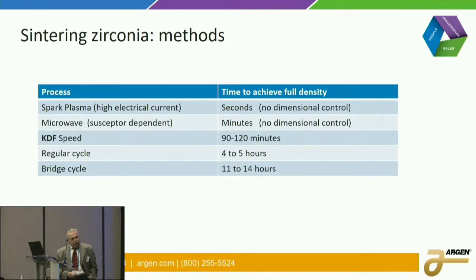Now, a regular cycle is 4 to 5 hours, and the bridge cycle is much longer. The bridge cycle is much longer because of what I mentioned before, and that is that zirconia does not conduct heat very fast, does not absorb heat very fast, and does not lose heat very fast. So when you have a lot of units put together, you have a lot of points of possible failure.